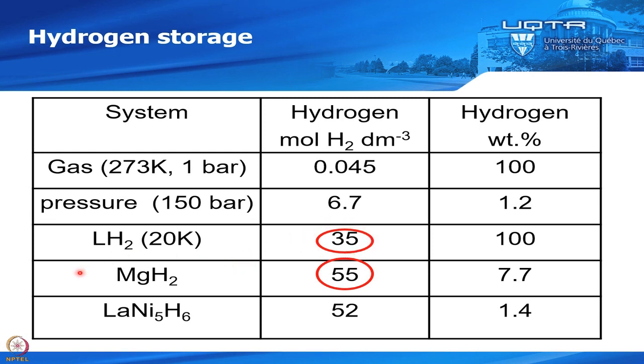But you see for metal hydride here, you have a high temperature metal hydride and you have a low temperature metal hydride. So this metal hydride is working at room temperature. This one is working at least 250 degrees C. And you see that actually it's a little bit counterintuitive, but the volumetric capacity of hydrogen is higher in a metal hydride than in a liquid. So the hydrogen atoms are more compact in a metal hydride than in a liquid. It's counterintuitive, but one of the best advantages of metal hydride is that hydrogen is compact, so your tank will be very small.